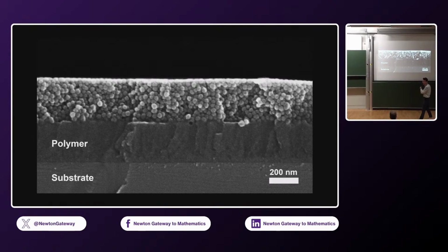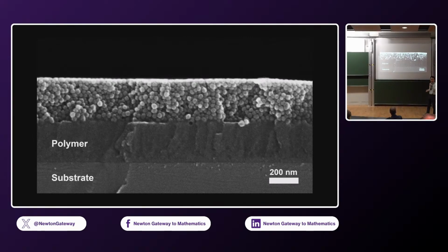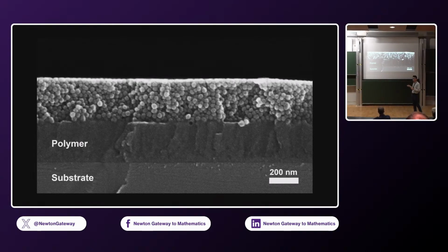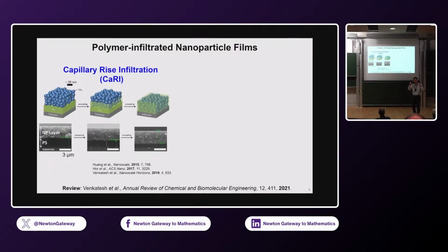One, we take this material, now this bilayer, and put that in an oven. When we put this in an oven and heat this above the glass transition temperature, the polymer now undergoes capillarity-driven infiltration into the interstitial pores of the nanoparticle packing. And as you can see here, when this happens, it almost looks like this nanoparticle layer sinks into the polymer layer, but it's not gravity driven because at some point it stops. I don't know if you can see it, but there's still a residual polymer layer here, but the nanoparticle layer stops sinking. So this is capillary driven.